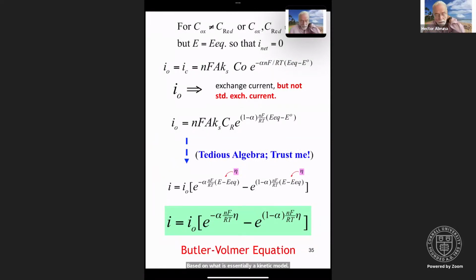So having to operate at standard potentials and in a very constrained environment is not really useful. And so we can take a few more liberties here. We can take the cases where the surface concentrations of ox and red are not equal, or not equal to 1, but we are at an equilibrium potential. If we are at an equilibrium potential, remember that's our definition for net current being equal to 0. So we can talk about an exchange current, I0, but not the standard exchange current density, because this is at a different potential.